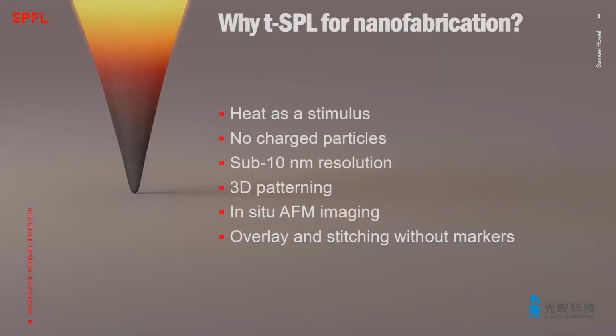Let us dive right into the reasons why TSPL is an excellent technique for direct write nanofabrication. First, it uses as a stimulus heat instead of charged particles, which means that structuring of low-dimensional materials and devices is possible without inducing defects, such as trapped charges. The technique reaches a lateral resolution of less than 10 nanometers in a single fabrication step. And 3D patterning is straightforward and directly related to the indentation depth of the tip.